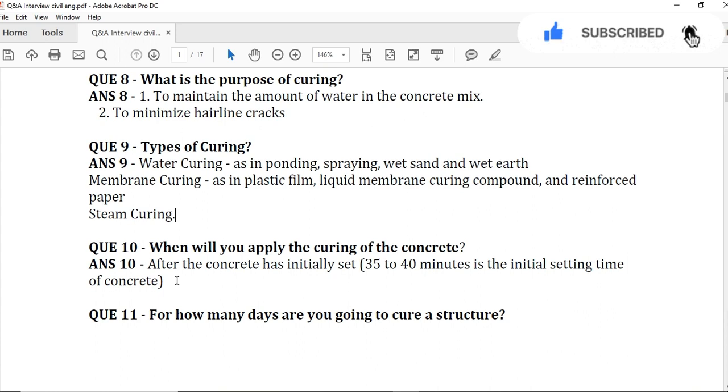Like if you cast concrete in the summer, so after casting you have to cover all the concrete with the plastic. So in daytime it will be avoided because the hydration in daytime is too much at the peak. And in daytime you can start maximum curing after 2 to 3 hours. But if you are using chemical for the curing, so you have to cover the concrete after 35 to 40 minutes or maximum 1 hour.